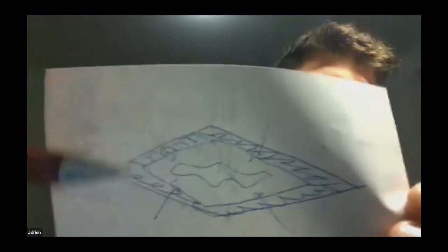So in the process after, we're going to cut here in the middle, and the point is going to be on the point. So we're going to have something that is very big to maintain. It's going to be something like this, a sort of big rectangle, and we are knocking the edges to get again this shape. I do it 3 times, and after I do a bar, a rectangular bar, okay? I often use 20 or 15 millimeters, not more thickness. After, in my experience, it's too thick. So I use a 20 millimeters thickness bar, long enough to be cut in 3 pieces.